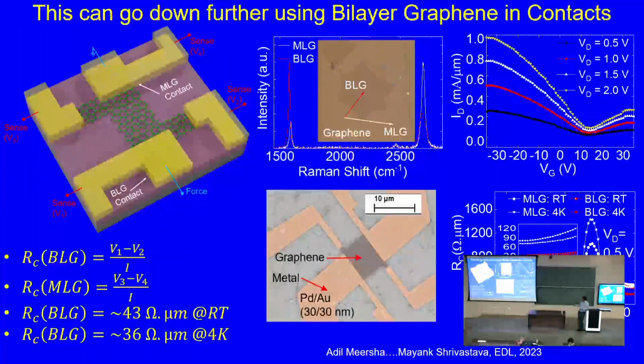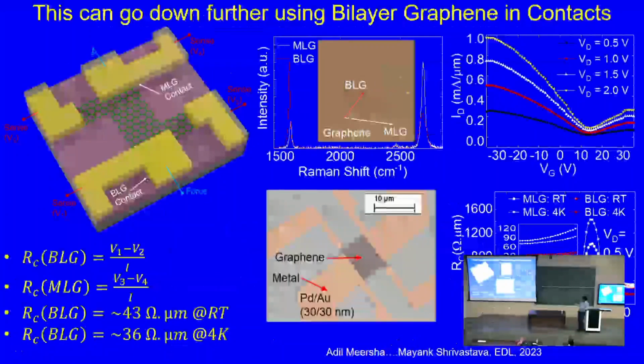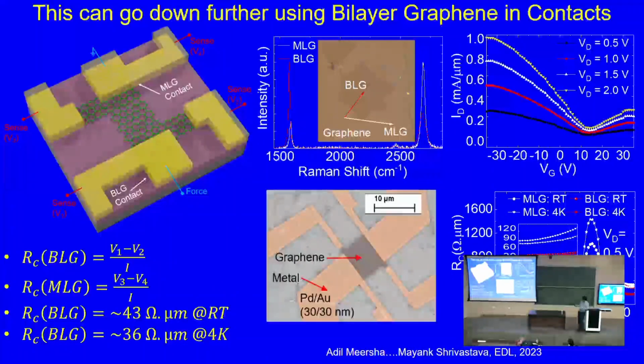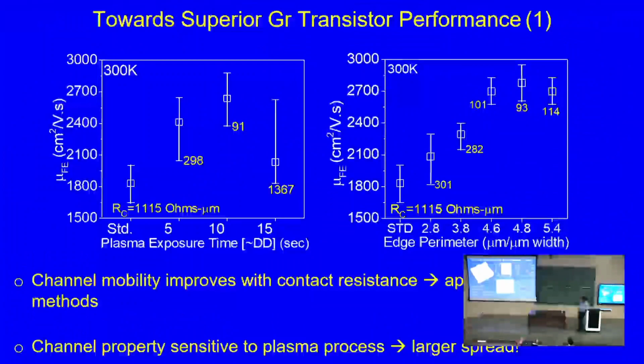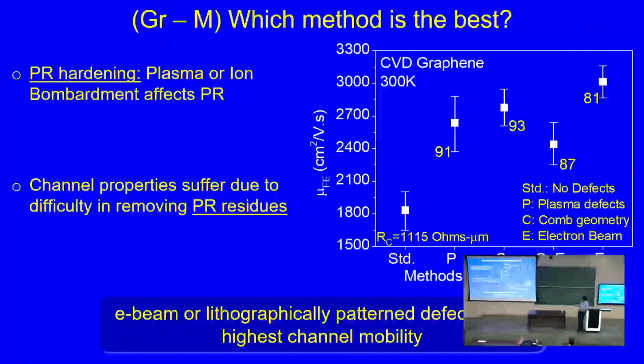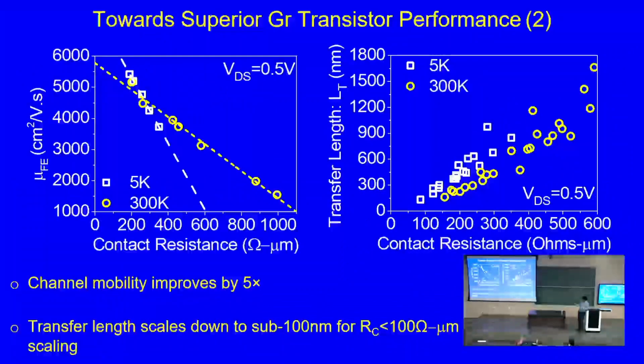And this is our recent work where we not only built these vacancies in the contact area, but also introduced another layer of graphene in the contact area. So it's a bilayer graphene in the contact area and monolayer in the channel, and that resulted in contact resistance in the range of around 34 ohm micrometer, 5 times below the quantum limit. So as you improve the contact, the mobility gets better. I'll skip some of these things.